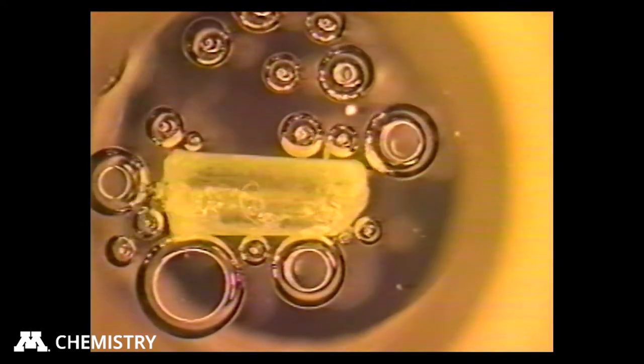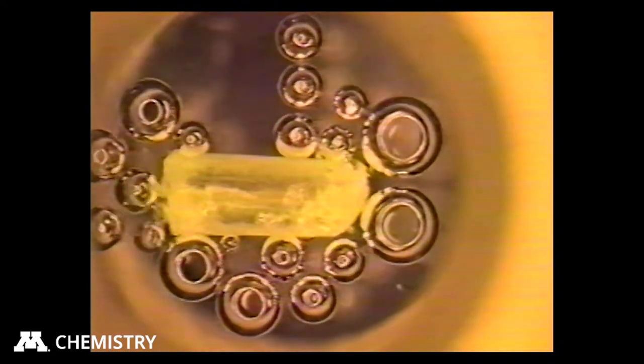Now, Professor Grant has studied this reaction in some detail, and he knows that at this point in time, 2 moles of water are being lost from the crystal structure. The third mole of water is being retained very tightly. And although I'm not going to show it on the videotape today, if we continued further to heat the temperature up to 170, 180, what you would find is that the crystal would be dormant, and the water would not continue to come off. And then at some point later, all of a sudden, water would start to come off very rapidly. This is the third mole of water being released from the crystal, and at that time, that crystal actually does break and crack into little pieces. And that's one of the unusual cases where that actually happens. So here you can visually see two different stages of dehydration.